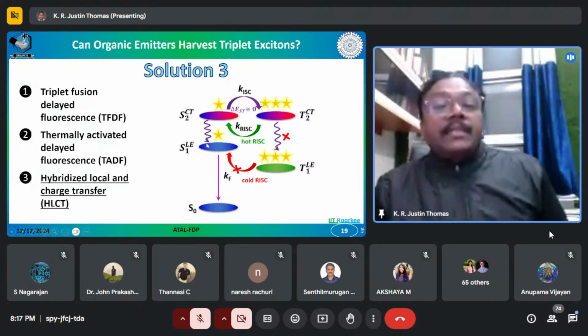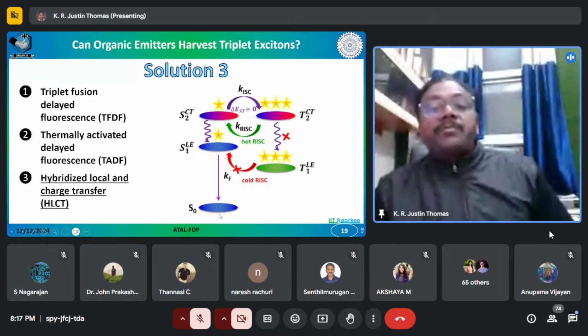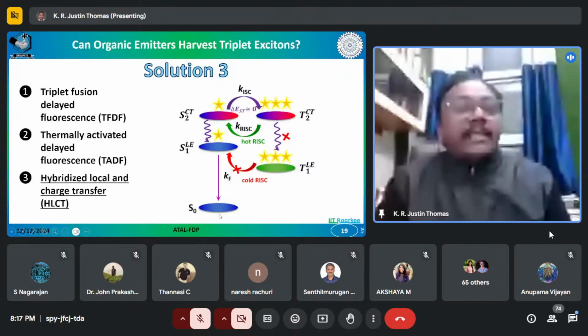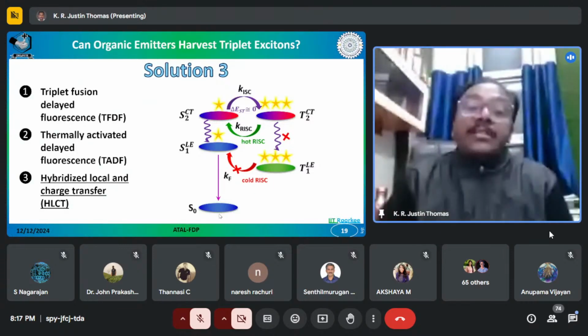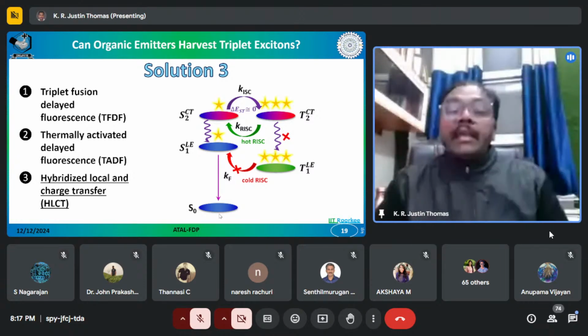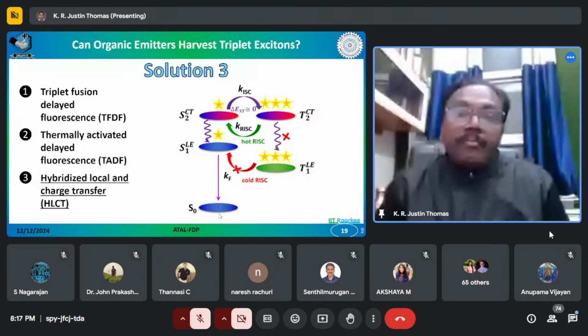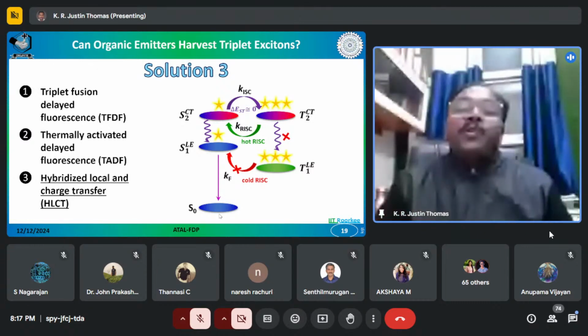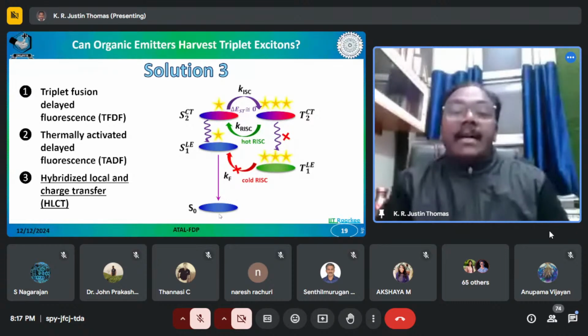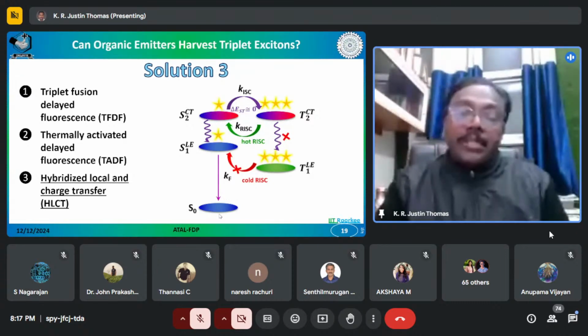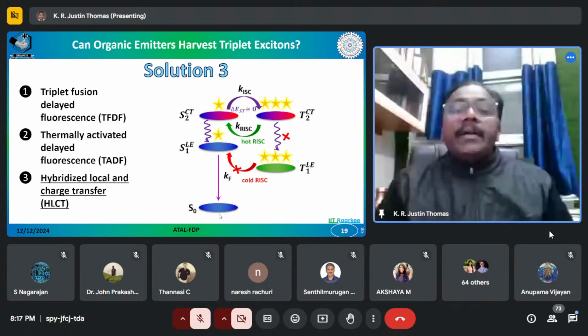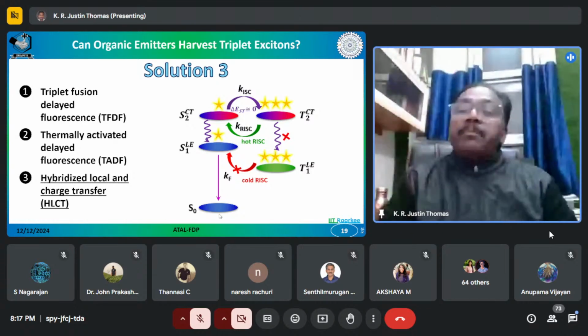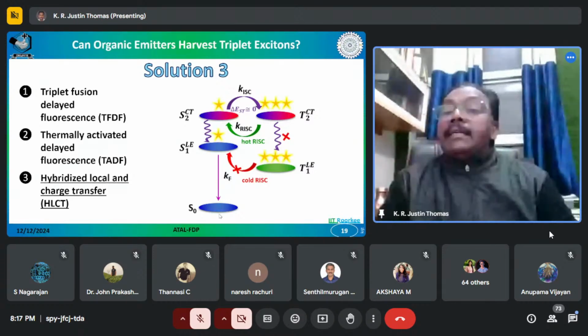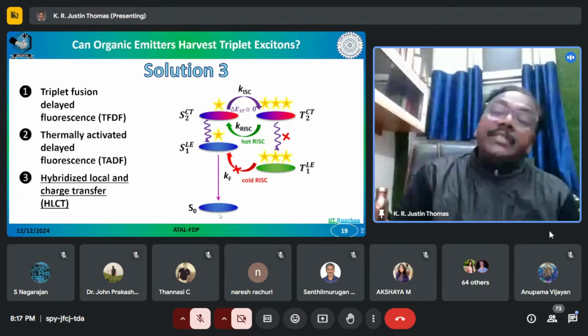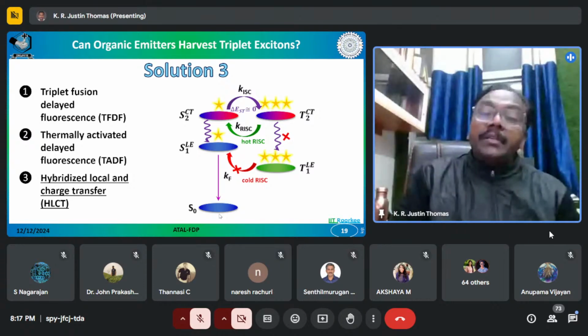And by a facile internal conversion, it will come to the S1 state, and then the emission will take place from the S1 state. Since the emission is taking place from a local excited state, that is a pi to pi star state, these molecules show a very high fluorescence quantum yield. The charge transfer state is only facilitating the hot RISC. Other than that, it has no influence on the emission characteristics. These kinds of molecules generally show very promising efficiency, however, their external quantum efficiencies are not very great when compared to the TADF materials.